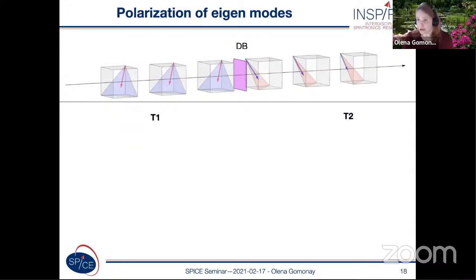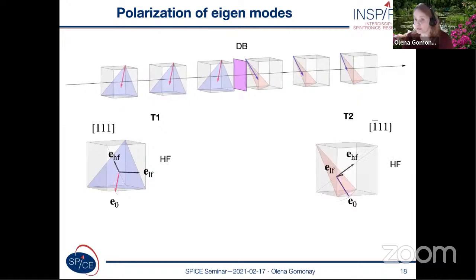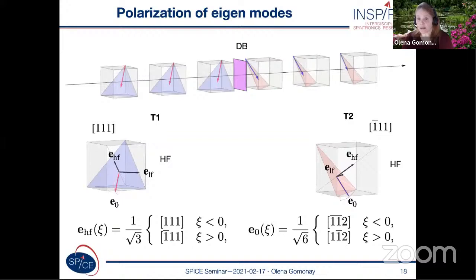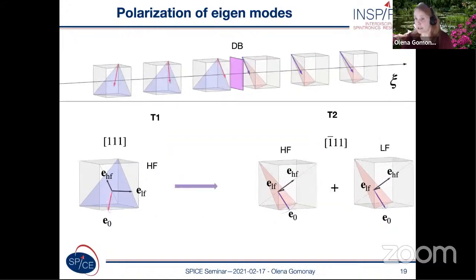The effect of such inhomogeneity we can feel when we look at the spectrum of magnon modes. So it's quite clear that the magnon eigenmodes of the homogeneous sample and a multi-domain sample should be different. And the considerations are very simple. So in a homogeneous sample in T1 domains, we have modes which are polarized out of plane, but in the other T2 domains, this out of plane direction is absolutely different. So this means that the mode which is polarized out of plane should split into 2, in and out of plane modes, when going through the domain wall boundary.